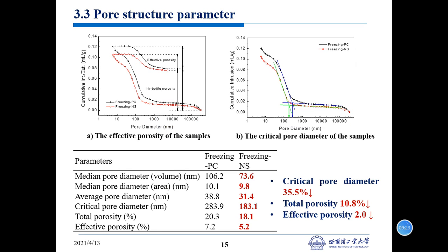This is the pore structure parameter. According to Professor Yan, the effective porosity and ink-bottle porosity are defined by this figure, and the effective porosity directly affects the permeability of the cement paste. So we can see the addition of nanosilica decreased the value of effective pores from 7.2% to 5.2%, but only a little change in the ink-bottle pores, like this.